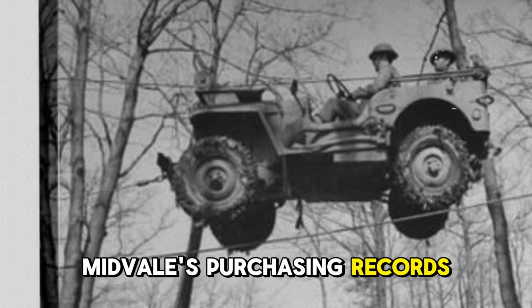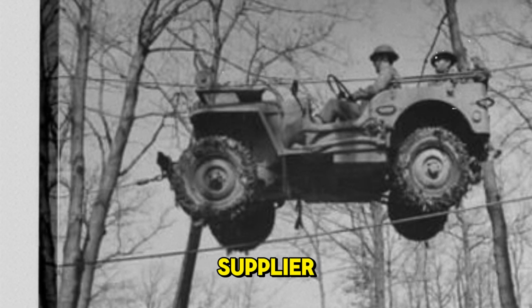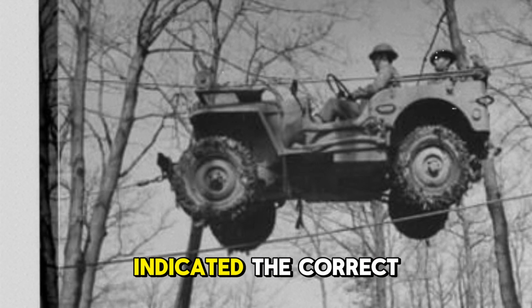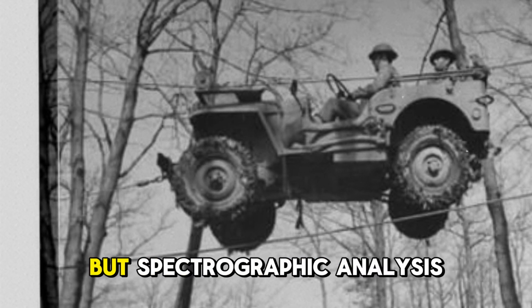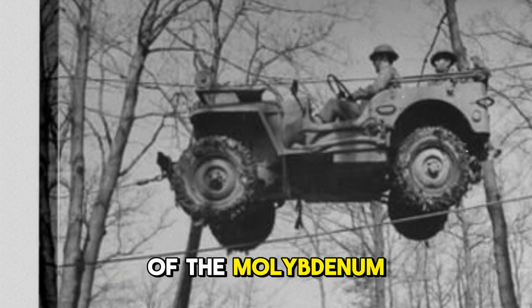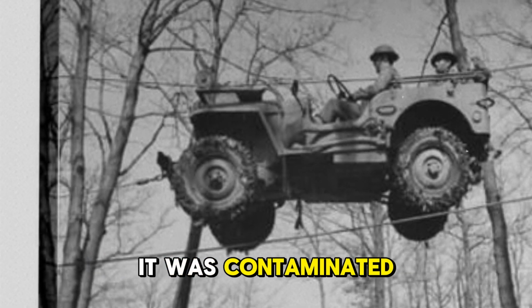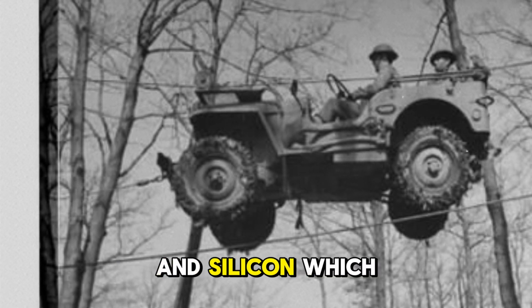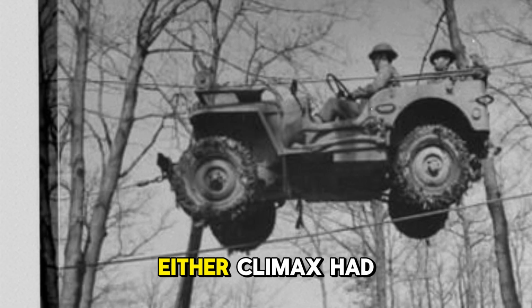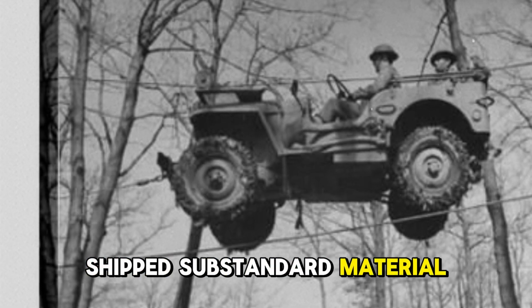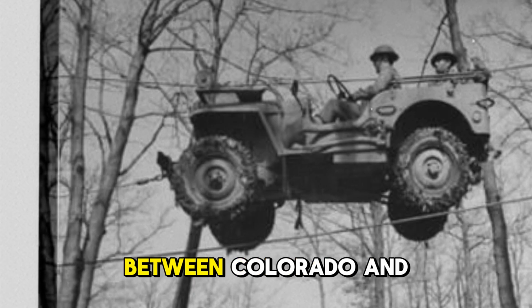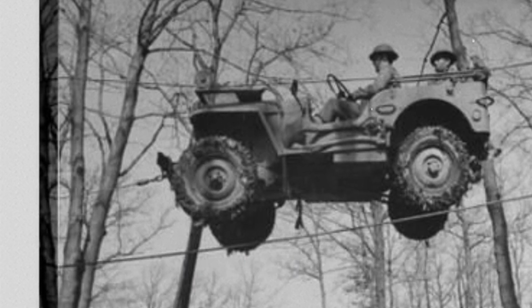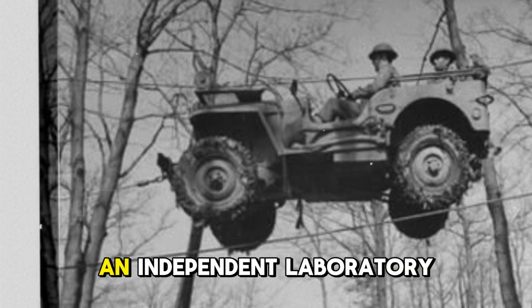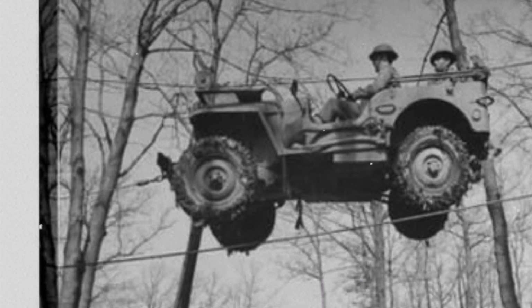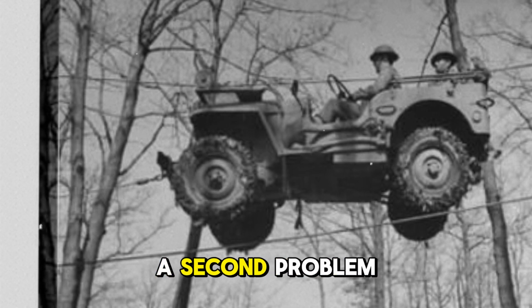Midvale's purchasing records showed they'd ordered molybdenum from their usual supplier, Climax Molybdenum Company in Colorado. The shipment manifests indicated the correct grade and quantity, but spectrographic analysis of the molybdenum actually used in production showed it was contaminated with excessive amounts of iron and silicon, which reduced its effectiveness. Either Climax had shipped substandard material, or something had happened to the molybdenum between Colorado and Pennsylvania. Moll requested samples be sent to an independent laboratory for verification. While waiting for those results, a second problem emerged.